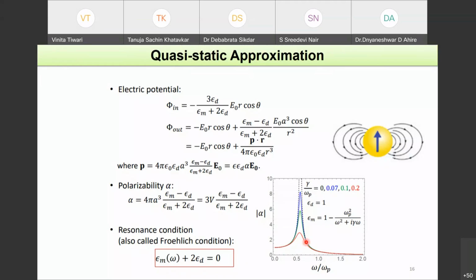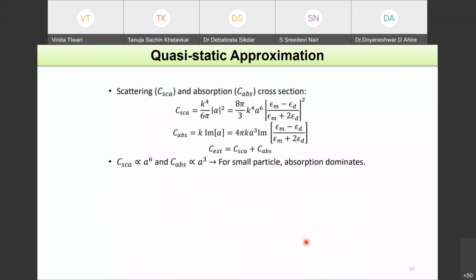Okay, so this basically tells you that you can approximate a tiny nanoparticle using a simple quasi-static approximation, and you can obtain the polarizability alpha. And once you obtain alpha, your life becomes very easy, because you can calculate the scattering cross-section and absorption cross-section using these very simple formulas. And then that can give you the extinction cross-section as well.